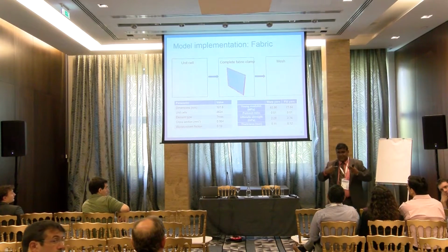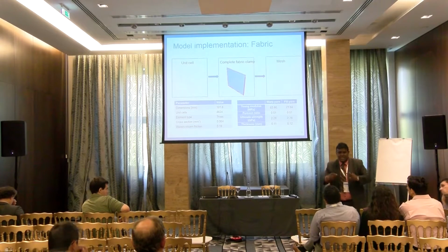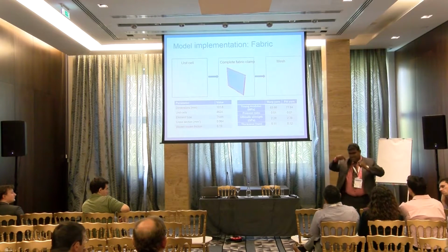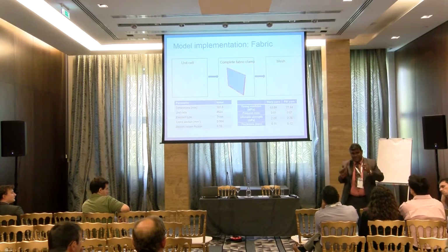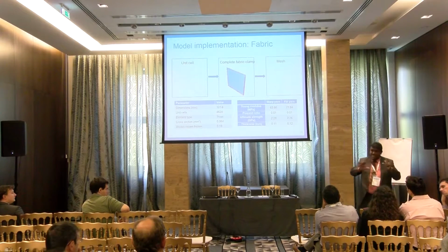Because, as I said, we ignore the bending, we are thinking as if we replace the fabric with a bunch of rubber bands. So we consider the transverse property doesn't matter because bending is not included. So only the axial property will matter. If we include bending, then the transverse property will be different than the longitudinal property, so we would have to use EX and EY for the yarn in that case. We have just truss elements.